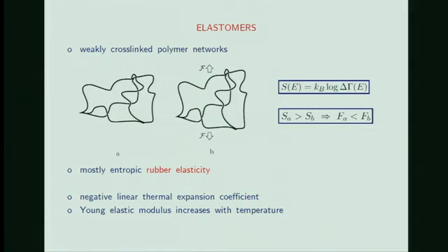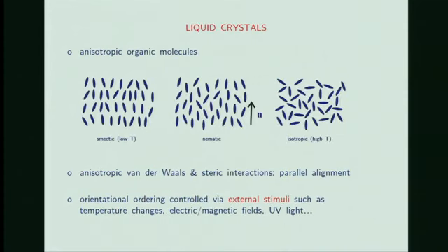There are some macroscopic manifestations of this phenomenon. One of them is a negative linear thermal expansion coefficient, and the other is a Young elastic modulus that increases with temperature. Then liquid crystals, okay, you've seen these pictures many times. For example, if we are talking of thermotropics, anisotropic organic molecules, you can change orientational order and positional order by temperature. So you have isotropic, nematic, and smectic phases.